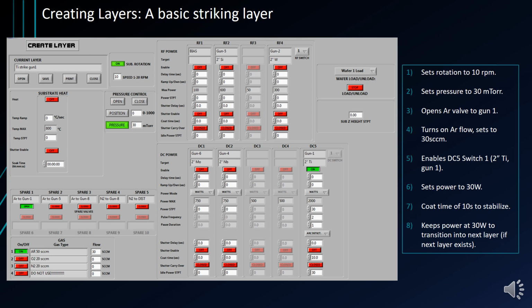Looking at the power supply section, you can see we've selected switch position 1 for DC5, which shows that it's connected to gun 1, which holds a titanium target. The gun is in watts mode and arc detect mode, which is normal DC when using the pulsed power supply. You can see that the delay and ramp time are set to 0. They aren't necessary when striking. The power has been set to 30 watts. Because there's no ramp time, the gun will abruptly apply that power.